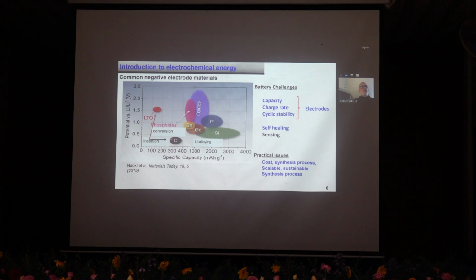So carbon is very mature, but it has quite low specific capacity compared to all those metals such as tin, germanium or silicon. So graphite is used commercially, but silicon theoretically could give a capacity which could be 10 times higher than graphite if we could use such materials.